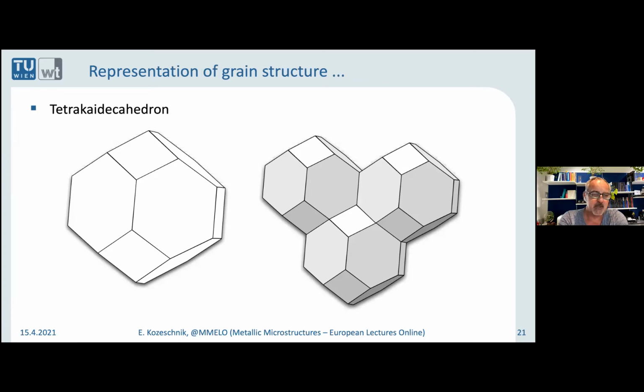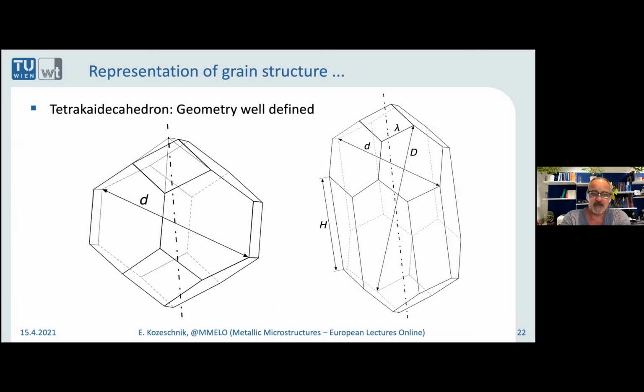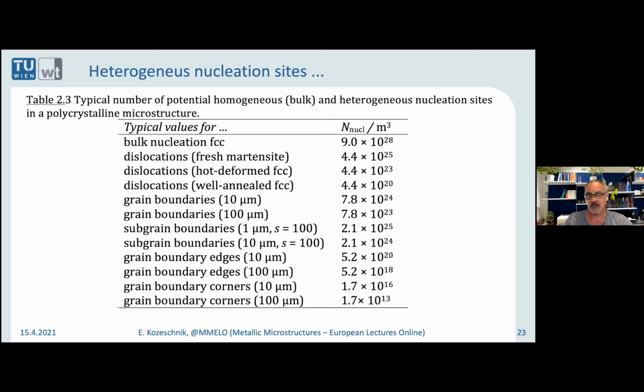And just a suggestion how we take that into account in our simulations: we model the grains as tetrakaidecahedrons, which are space-filling objects. And the advantage of that is it's very easy to define, let's say, a grain size. And from that, you can very easily calculate the volume of the grain, the surface area of the grain. You can easily calculate the length of the grain boundary edges and also count the grain boundary corners. Now, when you take that into account and when you think about nucleation always occurring on heterogeneous sites, then you can define the number of possible positions in your microstructure very easily.